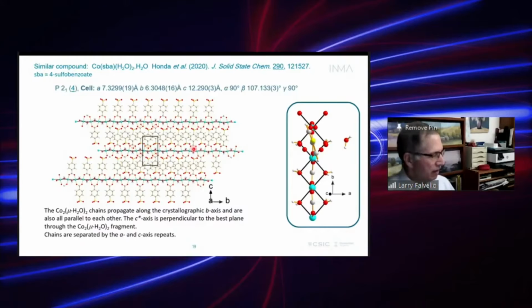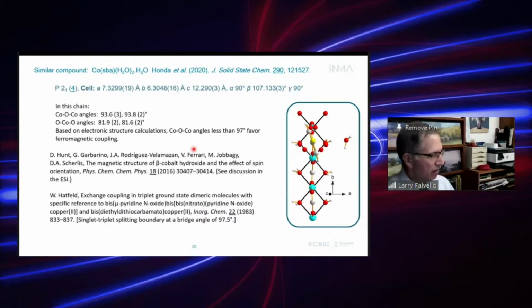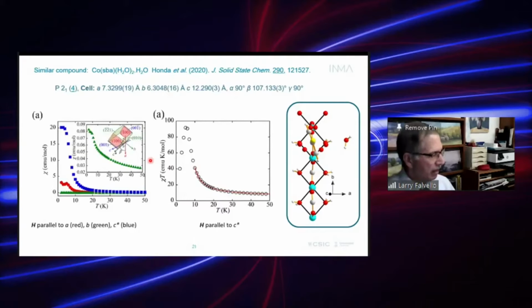So in this slide we have two references that they give for this limiting angle of 97 degrees. They measured magnetic susceptibility in single crystals with the magnetic field parallel to AB and to C star. This being monoclinic, C star is the axis that's perpendicular to A and B. So A, B, and C star form an orthogonal set.